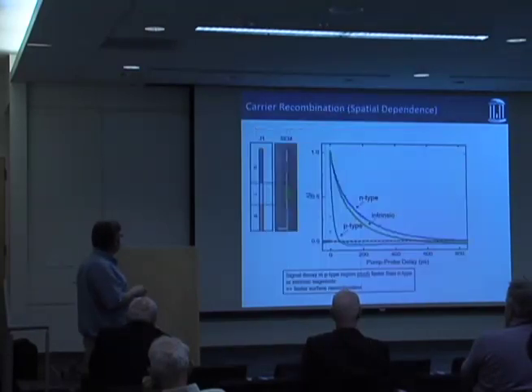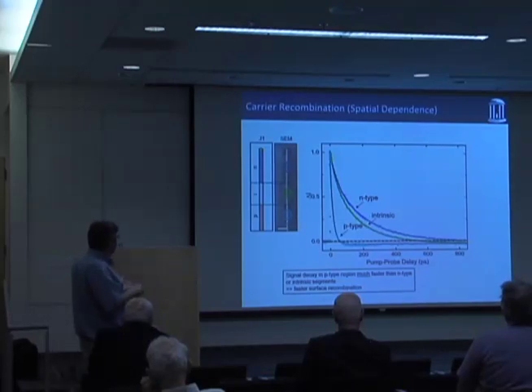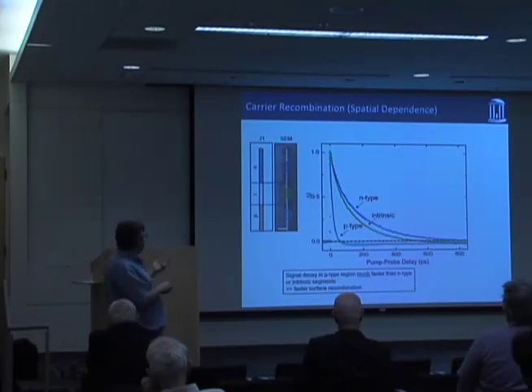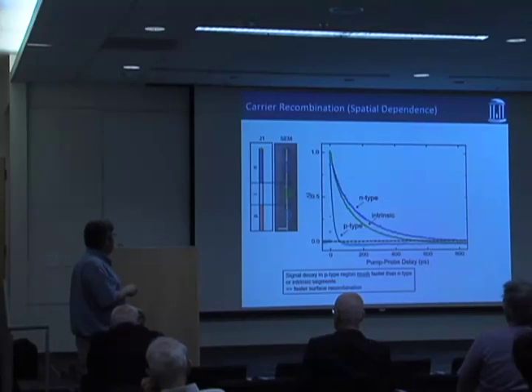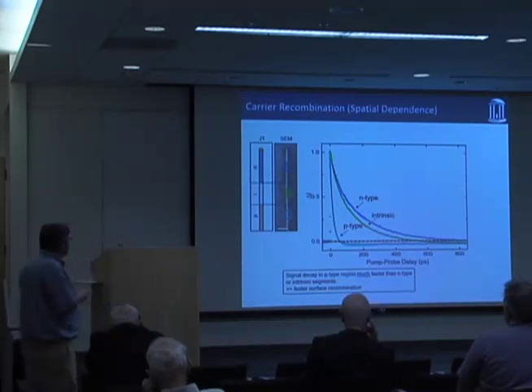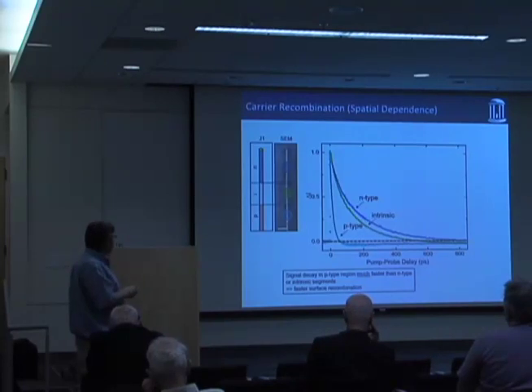Okay, so the first experiment we did was just to look at the carrier lifetimes in these different regions. If I do this pump probe experiment in the N-type or the intrinsic undoped regions, you see similar decay kinetics. But if I look in the P-type region, it's much faster. At first we thought this was maybe unique to this sample. This was the first time we really looked at P-type silicon. But it turns out we've looked at lots of other P-type samples now, and the recombination is just faster than the intrinsic or the N-type. And we're not 100% sure why that is. But nevertheless, it is faster.